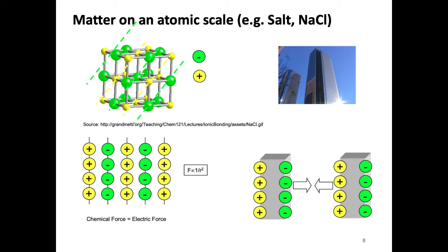But because of the superposition of repulsive and attractive force, you can calculate the Madelung constant that will roughly give you the bonding force between these planes. And still, you can understand the force is enormous. So if you play with these planes, for example, if you remove one of the planes, you immediately set up an internal electric field that will destabilize the matter. And that is related to the screening process of oxide surfaces.